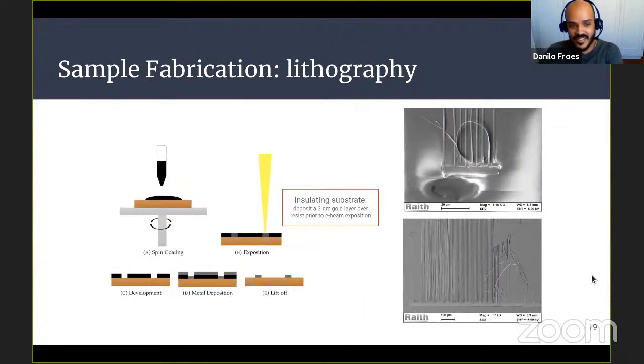Okay, so for the sample fabrication, we employed electron beam lithography. I'm showing this here on the right because it was very challenging to do, as our substrates were very insulating. Both the zinc oxide, the YIG and the GGG were very insulating. It's very hard to do electron beam lithography on insulating substrates because there are lots of charging effects. We could only do the lithography by depositing a 3 nanometer gold layer on top of the resist prior to exposure. So this was a technique we had to develop. It took some months of my PhD time to find out how to do that.